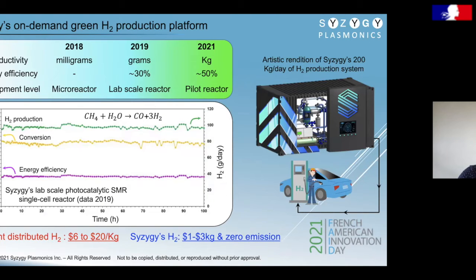In terms of technology development, over the past 3 years, we have been able to achieve more than 500,000 times increase in productivity, starting from 2018, when we were producing a few milligrams of hydrogen per day from a microreactor system, to 2019, where we were able to produce several grams of hydrogen with the lab scale reactor, and in early 2021, we were able to produce several kg of hydrogen from our prototype pilot reactor with a 50% energy efficiency. So it's ready to go.